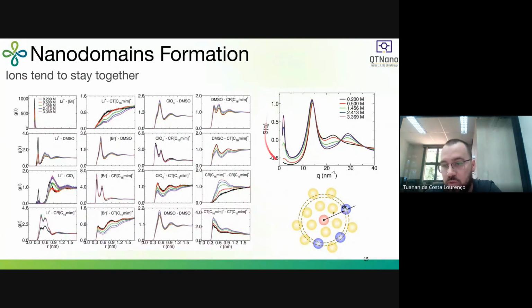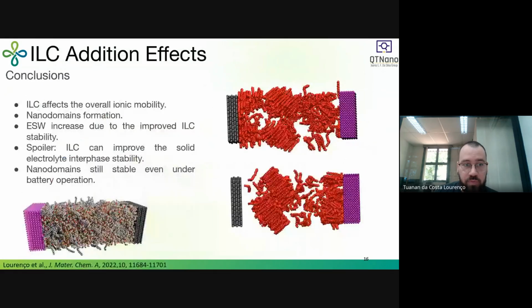Also, if you look here at the structure factor, we see that when we increase the concentration of ionic liquid, there is an increase in this first peak here that indicates the formation of this ionic aggregation and nanodomains inside the electrolyte. So doing MD simulations and experimental data, we were able to understand what is happening from the atomistic point of view in the structure and how this reflects on the transport and the performance of the electrolyte.